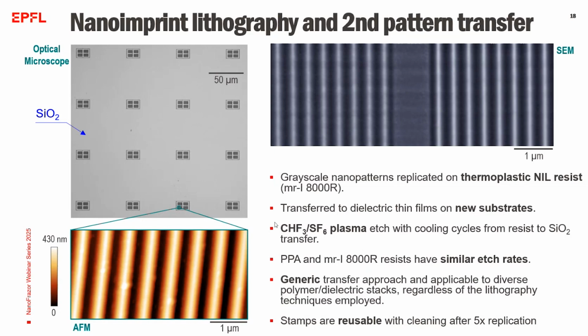And for the final pattern transfer from the thermoplastic resist to SiO2 on the new substrate, the same plasma recipe, which was developed for PPA and SiO2, is also used in this case, achieving the same amplification and roughness control. Therefore, we can conclude that the reported pattern amplification recipes are generic and applicable to various polymer dielectric stacks, regardless of the lithography technique used. And finally, these nano-imprint stamps can be used as many times as possible, but preferably with cleaning after every 4 to 5 times replication.